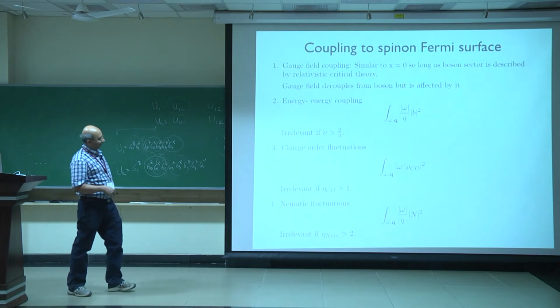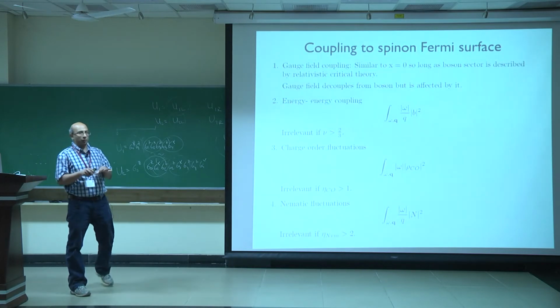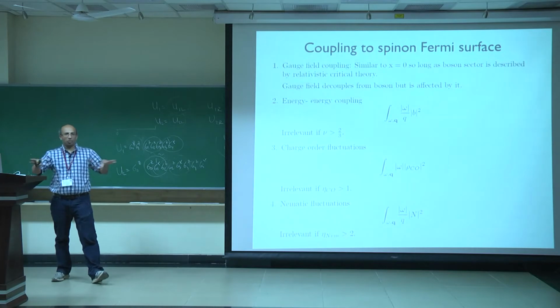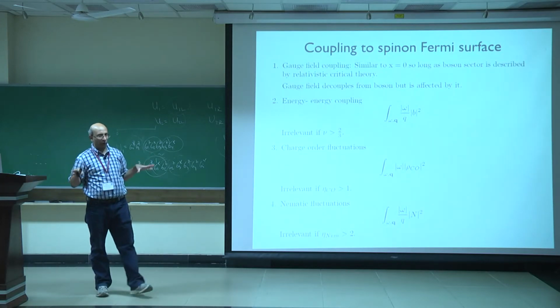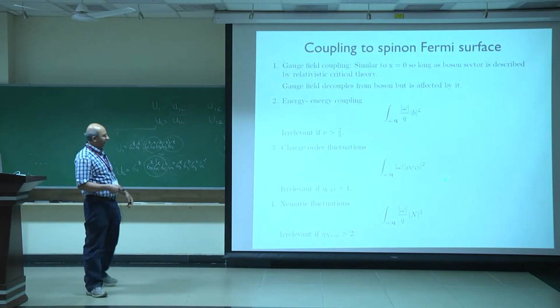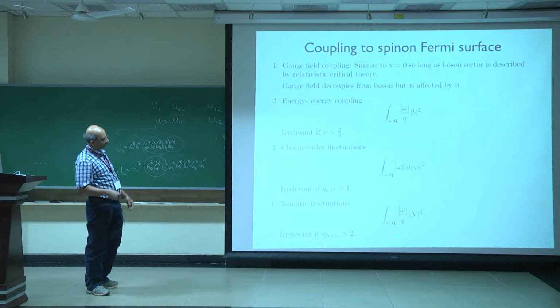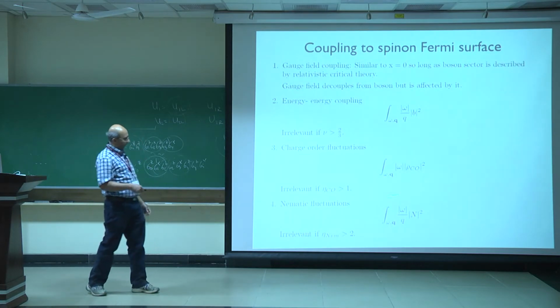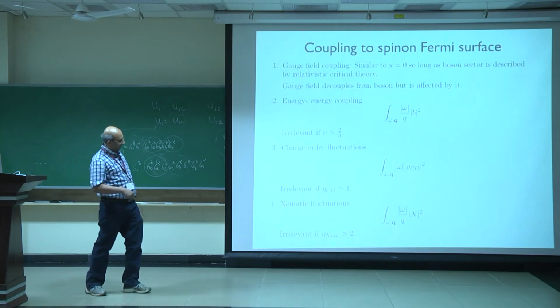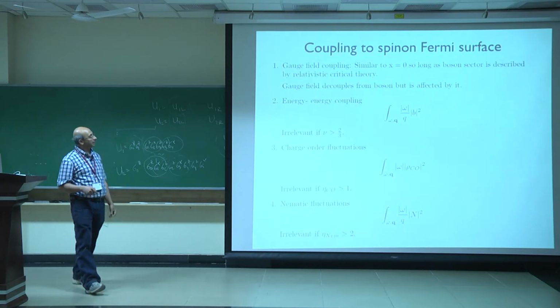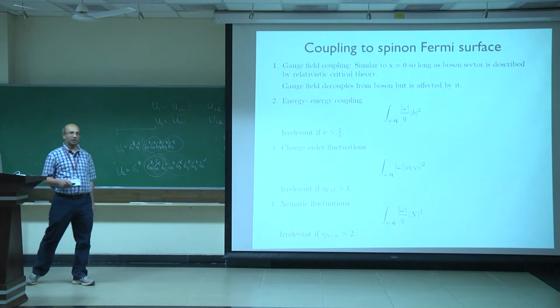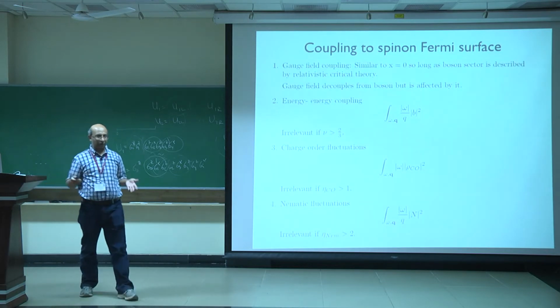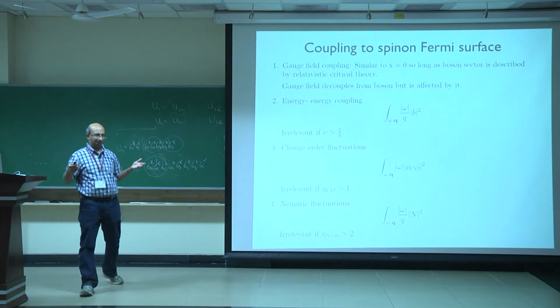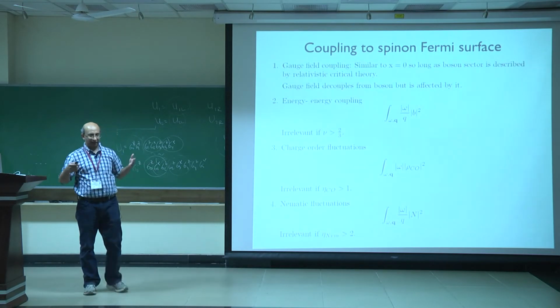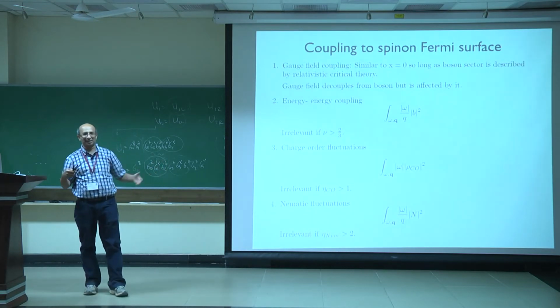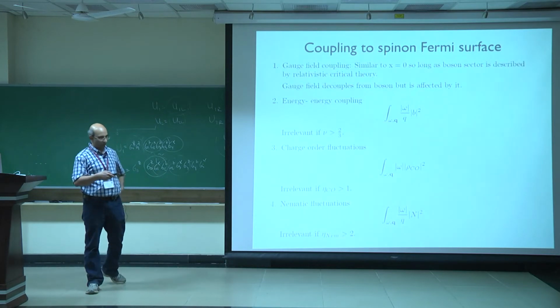And similarly, the nematic fluctuations, which sit at q equals 0, will couple to all points of the spinon Fermi surface. And so their damping will be stronger. And for them to be irrelevant at the bosonic critical point, you need this eta exponent for the nematic fluctuations to be bigger than 2. So we have a set of criteria for when the spinon sector fluctuations decouple dynamically from the boson fluctuations.